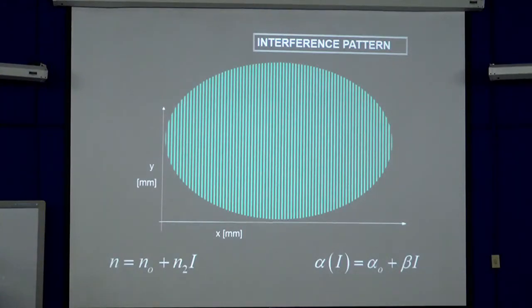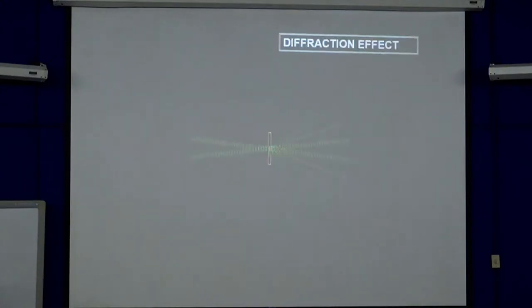So now what is going to happen when a particle, which can be energy or material, interacts with this grating? If we have this grating modulated by intensity, the index of refraction of a material is related to a constant, a property of the material, and the intensity. So the index of refraction, if this represents the spot of the beam, is going to be modulated with dependence on intensity, and also the absorption, which is related to a constant of the material, in product with intensity. We have two different gratings in the same region, one for refractive index and one for nonlinear optical absorption. So this grating generates diffraction.